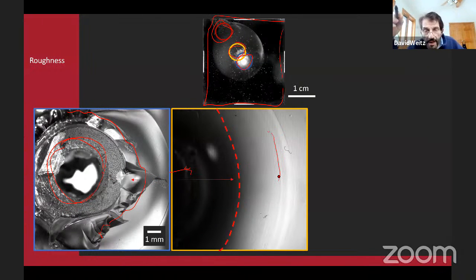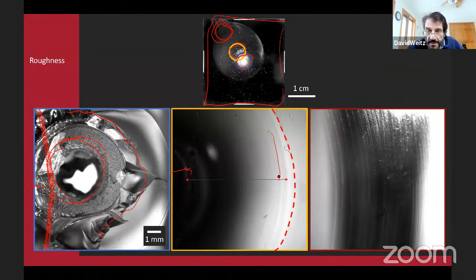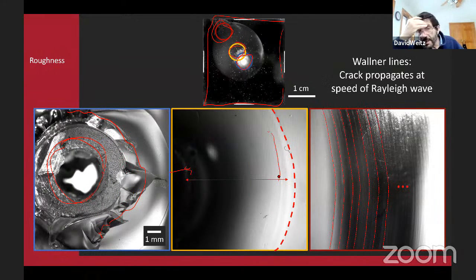And if you look farther out, you see more rings. And these rings are called Wallner lines. You get this very characteristic periodic roughness that occurs when the fracture is moving at the speed of the Rayleigh wave. This is something Franz Pfeiffer pointed out to us, that this is real evidence. The fact that we can see these Wallner lines is real evidence that when the fracture is moving, it's moving in a stick-slip motion, but when it moves really at the speed of the Rayleigh wave.